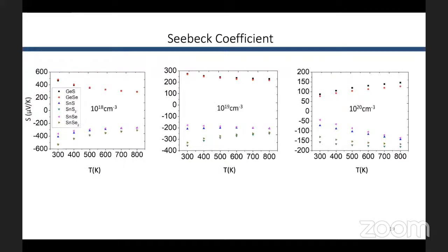And the Seebeck coefficient, as you see here, the absolute values of Seebeck coefficients exhibit a decreasing trend with temperature at 10 to the 18 and 10 to the 19 carrier concentration, with the exception of tin sulfide, where the change is small. Well, I didn't mention the materials. This is germanium sulfide, germanium selenide, tin sulfide, tin disulfide, tin selenide, and tin diselenide.